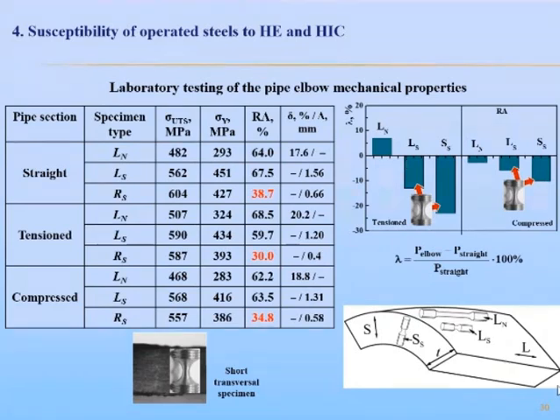standard smooth cylindrical specimens and also notched specimens in order to estimate mechanical properties. Longitudinal and cross transversal specimens were tested. And the pipe elbow steel was characterized by lower plasticity in comparison with the straight pipe run, regardless of whether the elbow section was tensioned or compressed.